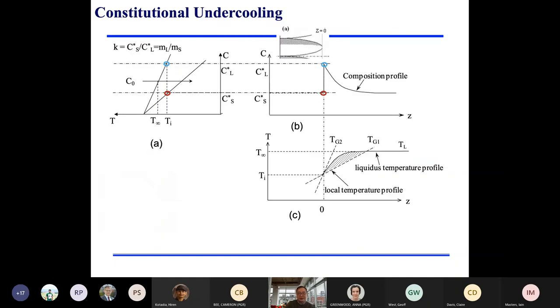So when we grow a crystal, what will happen? Essentially this will be the control equation. Because the solid and liquid have different chemistry, and you grow at this velocity, those concentrations are different. Essentially, those solute atoms will be pushed into the liquid from the interface. That amount of solute will be pushed into the liquid phase, and then your liquid phase will have high concentration. Because the liquid phase is determined at this point, you have a concentration jump at the interface, and this will decay away.